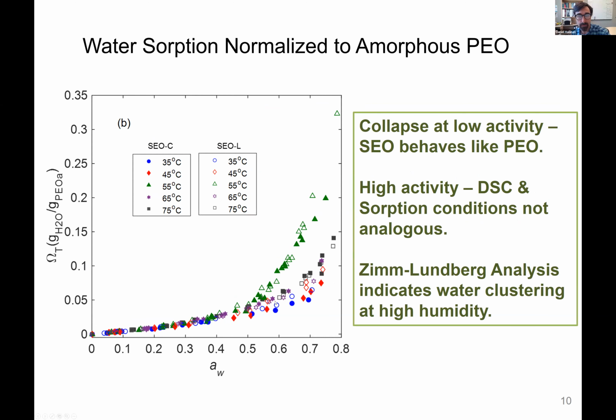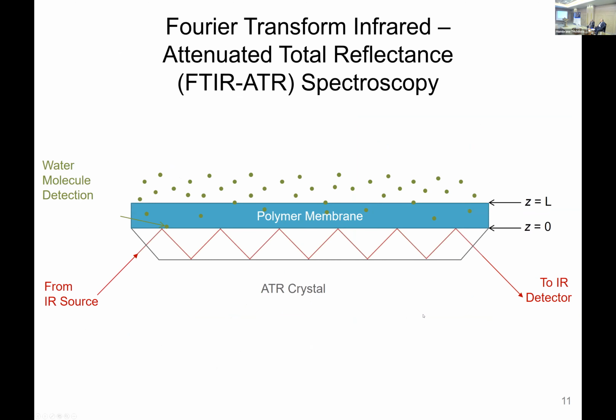The other interesting thing we found is if we did a Zimm-Lundberg analysis, we found that water is actually clustering at these high humidities inside the polymer. In other words, at low humidities, it's individual water molecules distributed through the free volume of the polymer, but at high humidities, it's clusters of water that appear to be present in the polymer.